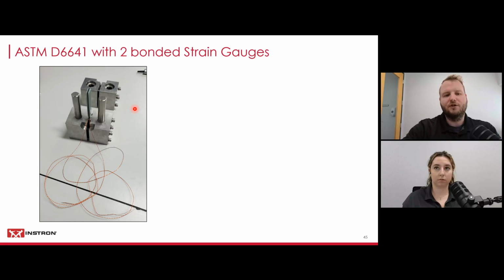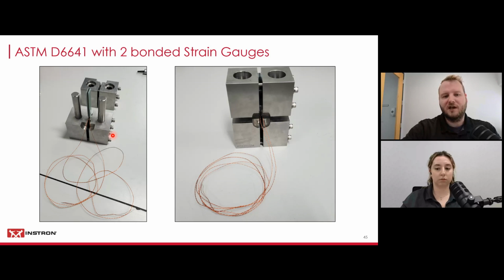So be careful when you're doing this with a strain gauge specimen. We don't want to get any damage there to the cabling or to the strain gauge itself. So this is how it looks when you start out putting the specimen in the lower part of the fixture with the alignment rods pointing upwards. You've got to make sure that you lead your cables out, and make sure that the specimen also fits into the fixture, right? So 140 millimeters length, I think, is the minimum. You could maybe get away with a little bit less, but that's definitely the recommendation within the testing standard.